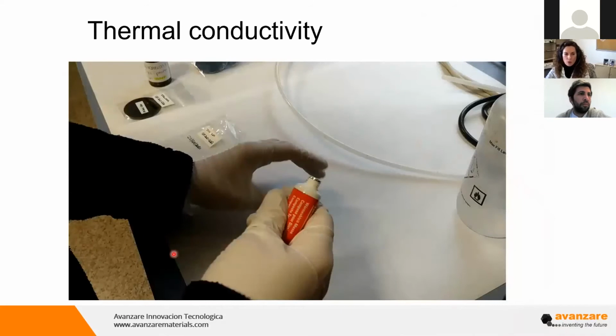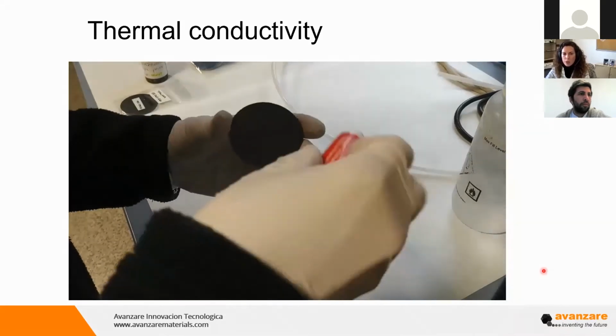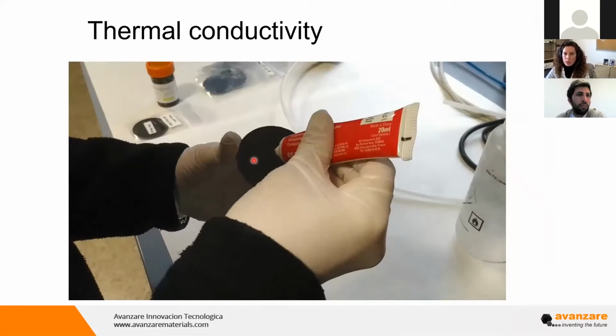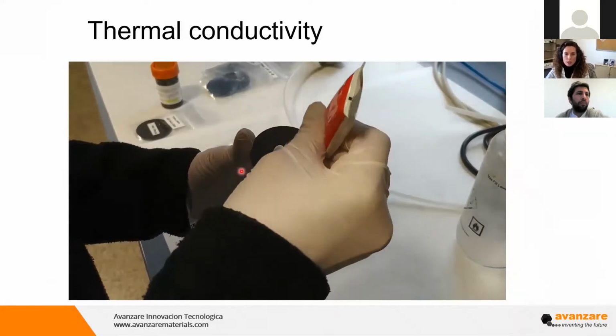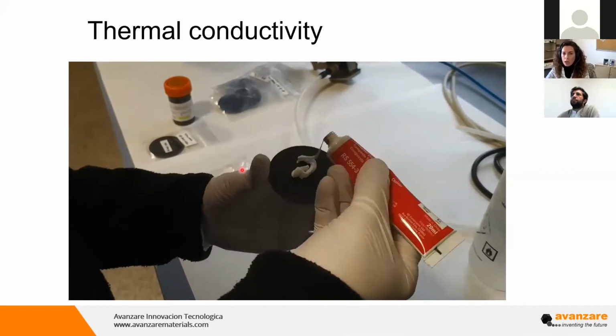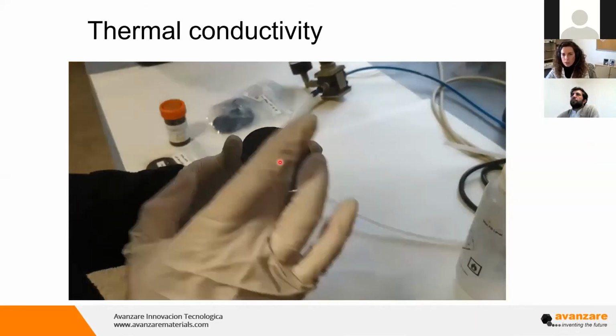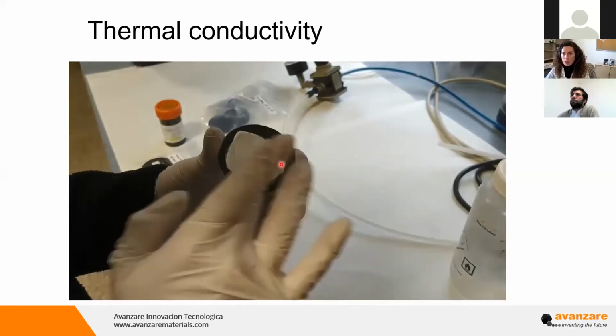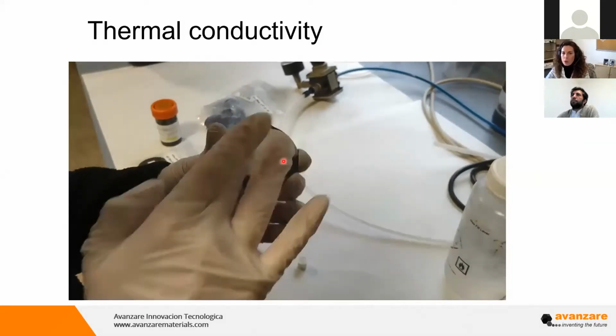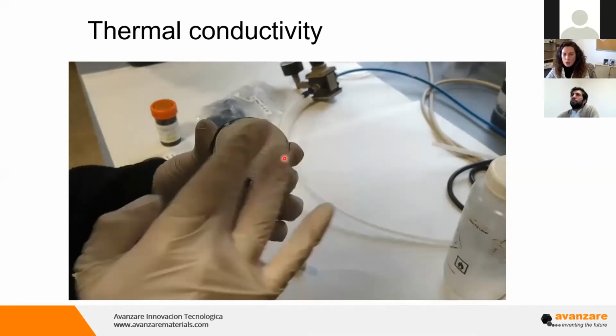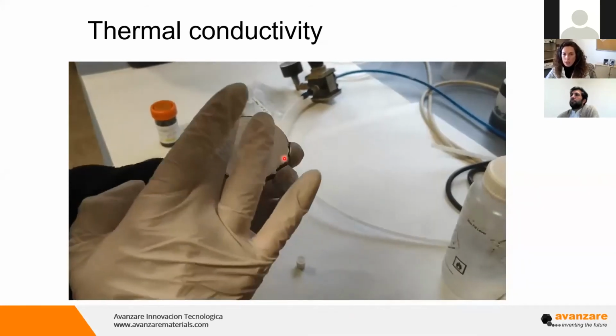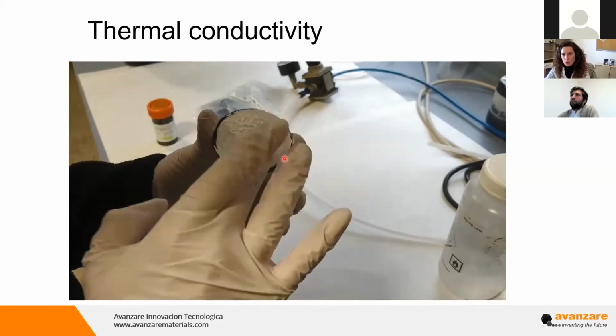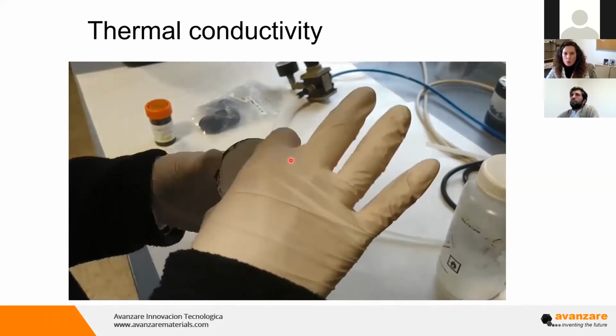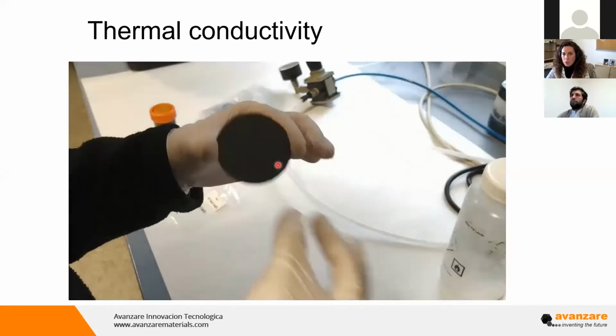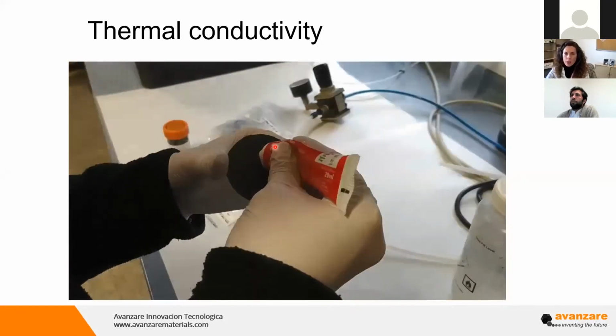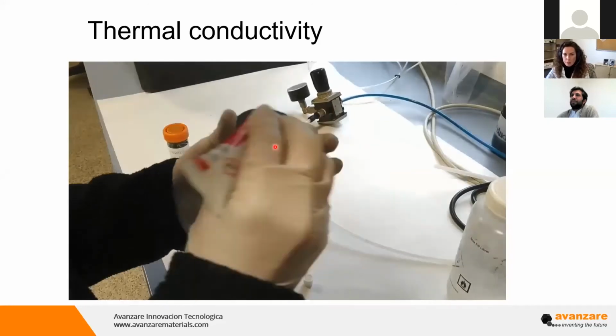This is the video of how we are measuring. This is a specimen with these flat and parallel faces. We are applying this special silicone paste of high thermal conductivity. It's necessary to apply it directly with your fingers to create this irregular surface, as you are going to see now, to avoid any loss of heat from the sample to the upper and lower plate. So we put this silicone paste on both sides of the sample, and we insert it in the cell.